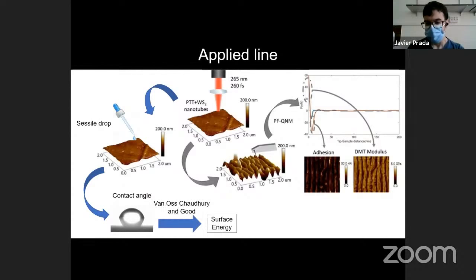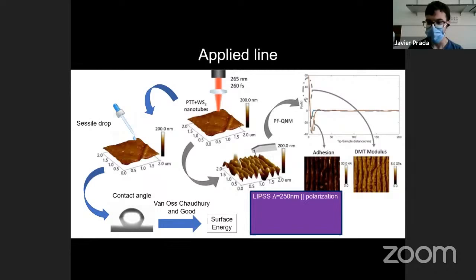We found that the same changes for the polymer and the nanocomposite were induced by irradiation. In the topography, we found that the structures have a period of 250 nanometers and form parallel to polarization. From the nanomechanical measurements, we find the Young modulus is preserved, but there is a decrease in adhesion. And from the contact angle measurements, we find that there is a hydrophilicity increase, but the total surface energy remains constant.